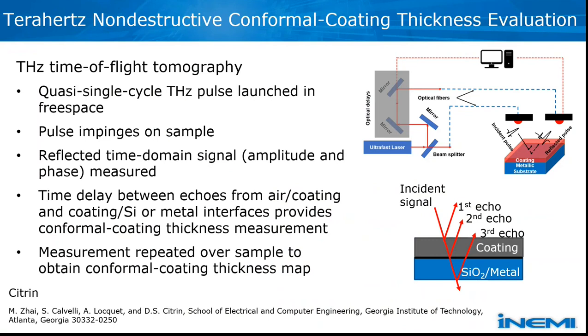The technique we're using - I'll talk about two. One is called terahertz time-of-flight tomography. A single-cycle terahertz pulse comes in, there's a reflection, and the reflected signal is made up of echoes that occur at the various interfaces in this layered structure. By knowing something about the material and measuring the time delay between the two echoes, we can learn about the thickness of that layer. Underneath the coating, we have either SiO2 or the metal film.